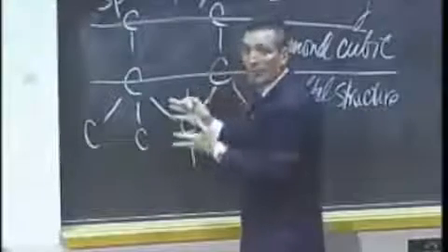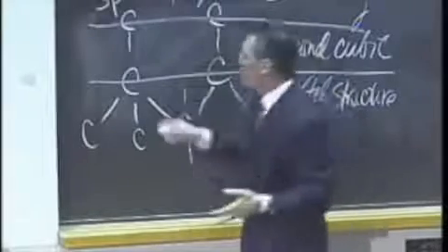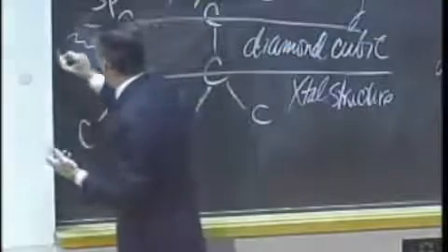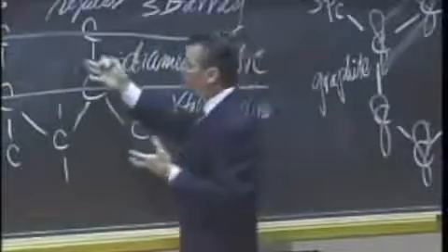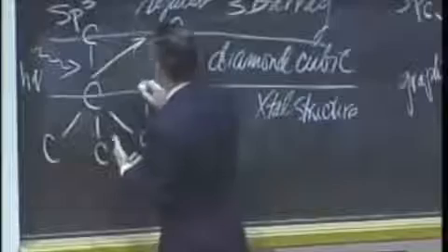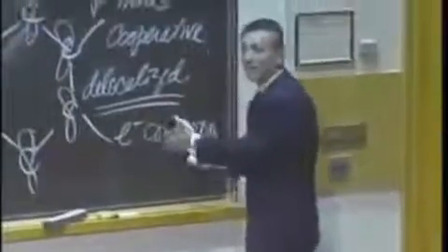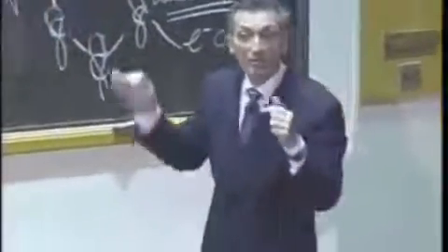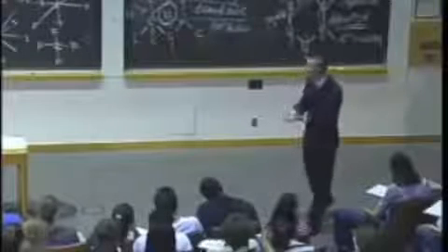What about the optical properties here? This one is transparent to visible light. Why? Because electrons are tightly bound. So you've got this really weak photon, visible light, 2 electron volt photon comes in, and it can't excite anything, but the bonds are so strong that it's refracted. So one of the properties of this is a very high refractive index. Whereas here, electronic conduction means it's got very, very low excitation, and hence graphite is an absorber. It appears black because any light that shines on it is absorbed.